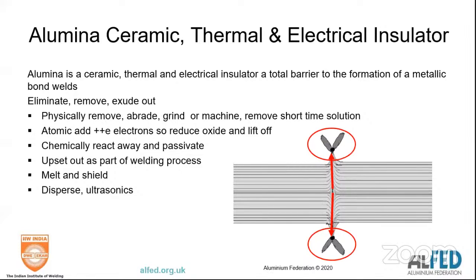If you're going to do very simple welding, very quick, you can physically remove the aluminium: abrade it away, grind it, machine it. But remember, you've got a short time interval. If you grind aluminium, potentially you've got, depending on your humidity and the temperature, 2 to 3 hours before that oxide starts to form.